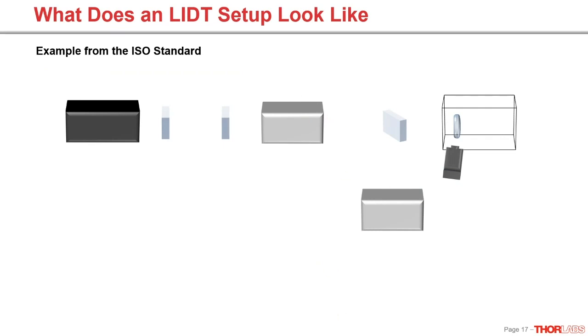So let's look at a typical laser damage setup. Obviously, number one, you need a laser system. Then you need a variable attenuator in order to ensure that you're not operating at 0 or 100% power. You need to be able to vary the power in order to get the damage. Then you're going to have some series of wave plates to get whatever arbitrary polarization is needed on the sample. Some parts are polarization sensitive, and you're going to want to test with a particular polarization, whether that's P, S, circular, or some other linear. You're going to need the wave plate for that.